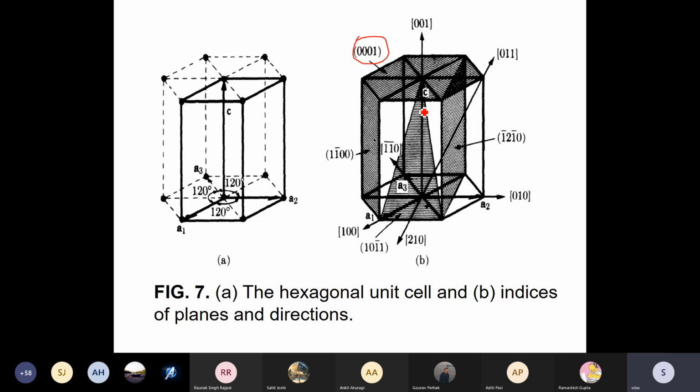Remember that. That battery has a graphite anode, means negative electrode. The way it is arranged, these parallel planes are there, 0001, 0001. Lithium ion during charging gets into the interlayer, between 0001 type planes, means this top plane, then this bottom plane, and so on. In between these planes, lithium ion gets in. It expands the lattice to a certain extent, but not to a great extent.